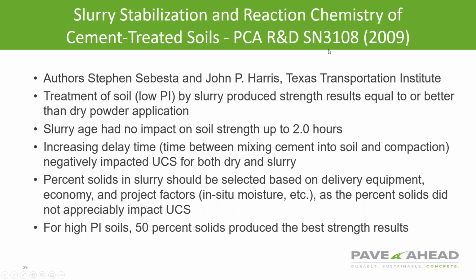And here you can see results of a study. This is actually an older study done in 2009. It was done by the Texas Transportation Institute. And here's some of the findings. As I mentioned, there's no difference in the strength results. Slurry age had no impact on soil strength up to a period of 2 hours. Increasing the delay time did negatively impact the unconfined compressive strength for both dry and slurry. And the percentage of solids in the slurry should be selected based on the delivery equipment. And for high PI soils, 50% solids produce the best strength results in this particular study that the Texas Transportation Institute provided.